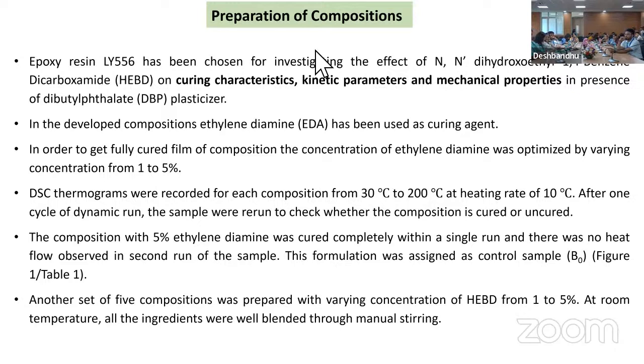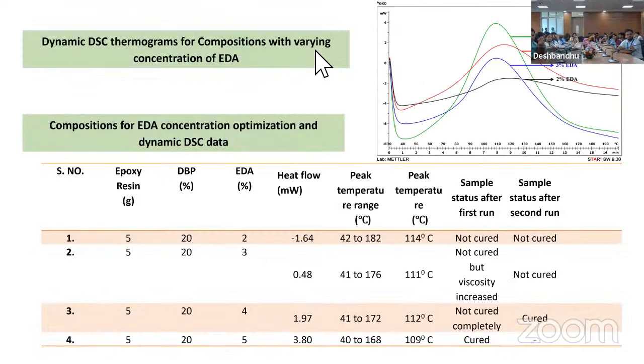For the preparation of formulations, we have selected epoxy resin LY556, and we have investigated the effect of this monomer on curing characteristics, kinetic parameters, and mechanical properties. Ethylene diamine has been used as curing agent. So we have checked the percentage of ethylene diamine needed to get the finally cured film. For this, we have recorded thermograms by varying the concentration of ethylene diamine from 2% to 3%, 4%, 5%.